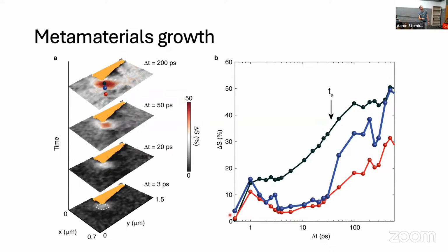First, if you look at a location in the interior of the film, you see, again, an increase of the near field amplitude, and then a decrease and a follow-up increase. Right after photoexcitation, you have an increase which is linearly proportional to fluence. And if you look right next to the antenna, you can see that there is an increase that's about 50% higher at this initial time delay, indicating there is a larger fluence or a larger electric field at this location.